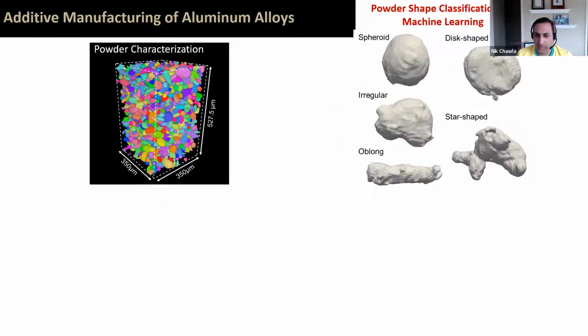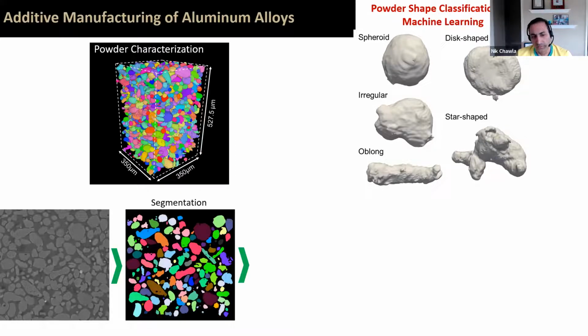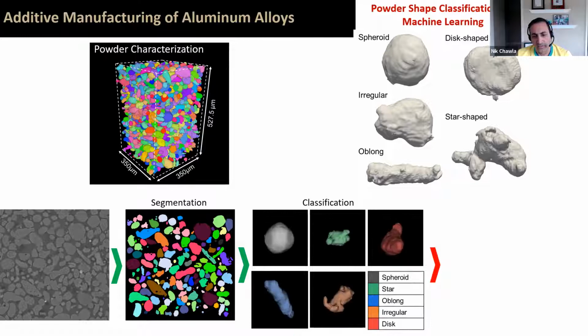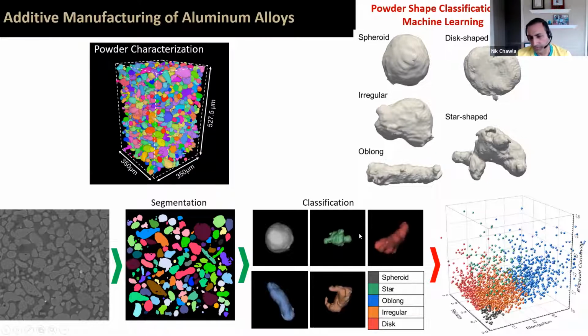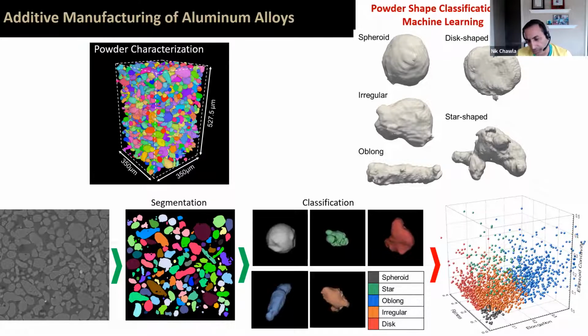Here's an example with additive manufacturing. In additive manufacturing, the shape of individual powder particles is very important in terms of powder flow, overall manufacturability, and solidification. So we're using tomography here to get the shapes of the particles. And here we're using machine learning as a classification tool. So we go through the image analysis. This is something that Daniel Sinclair and Ishan are working on. And you get the classification, and then you can use different kinds of techniques to classify a perfectly spherical particle versus one that's more oblong, more like a stick, or something that's more like a disc.